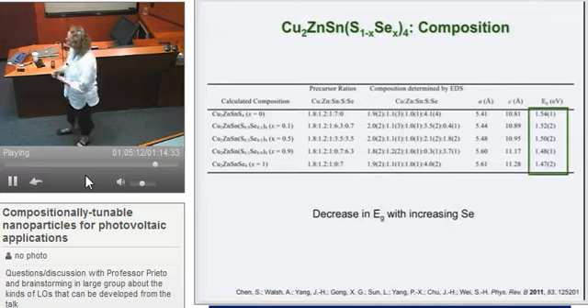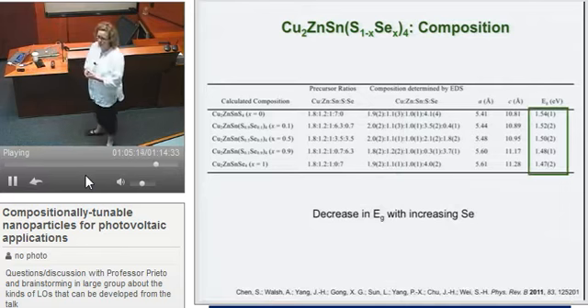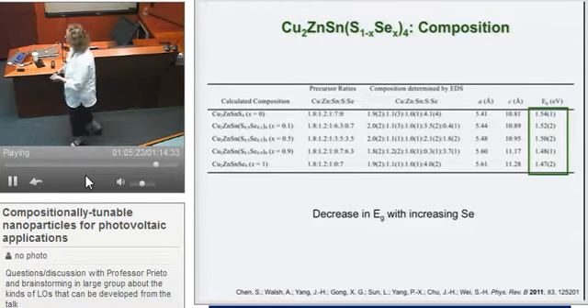But the surprising result was the band gap. I told you that theorists predicted 100% selenium should give you a band gap of 1 eV, and you don't see that. You do see a decrease, but not by as much as you would expect.